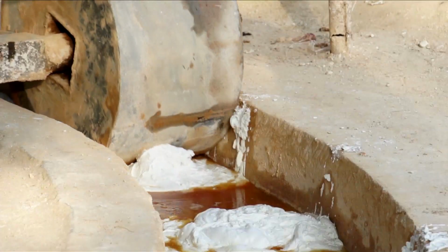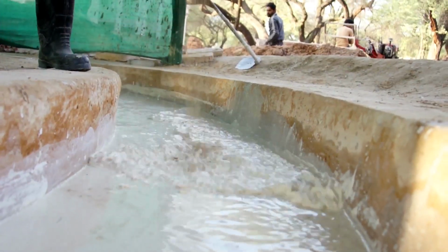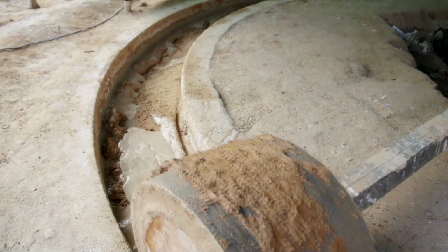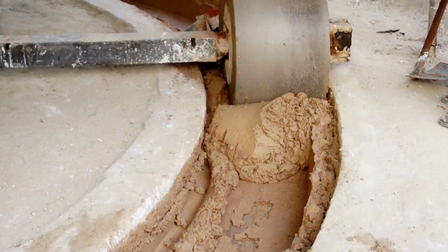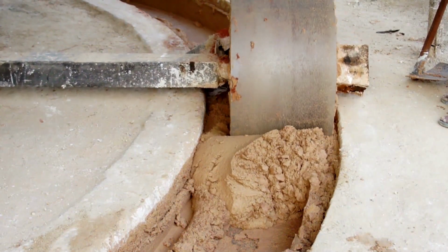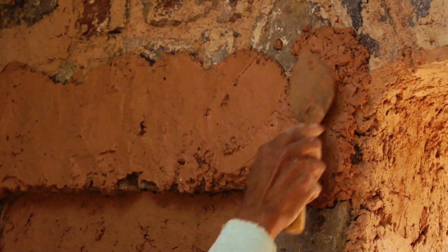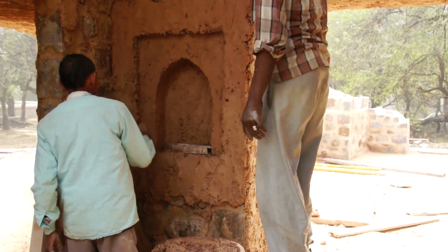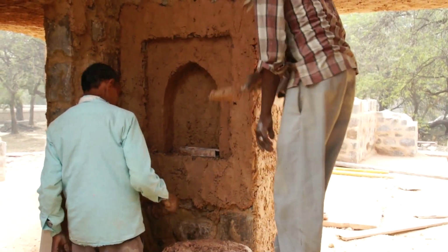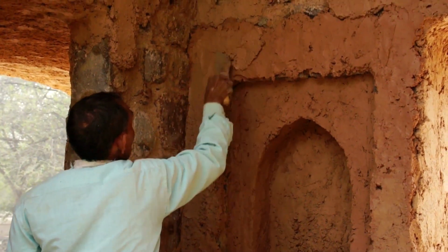These mixes make the construction more durable, weather resistant, and allow it to gain strength. It is estimated that stone masonry with lime mortar reaches peak strength often 3 years after being built. Lime mortar is porous and allows dampness to pass through, thus protecting the sandstone masonry from the harmful salts that are usually contained in the dampness.